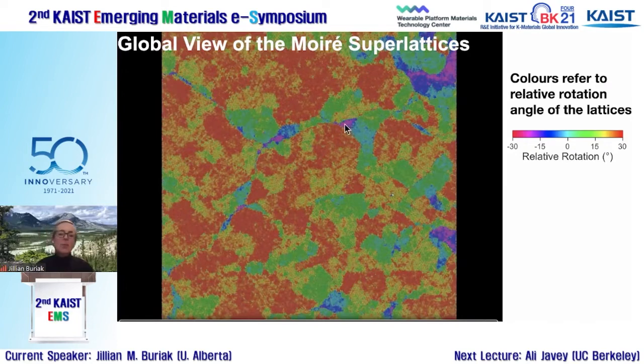And the purpley flower phases of the defect sites are actually forming where you have a lot of defects where grains are meeting underneath. And so the system's so frustrated, it doesn't know what to do. But once we have a statistical way to do the stats on these things, we can actually determine whether or not these are majority phases.